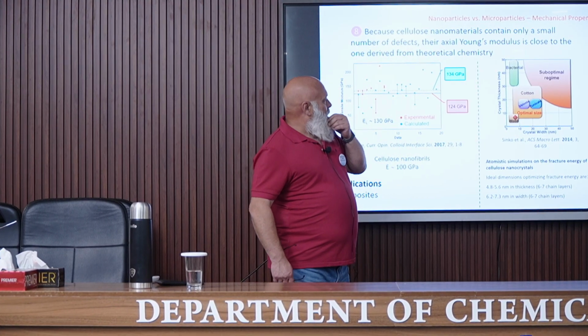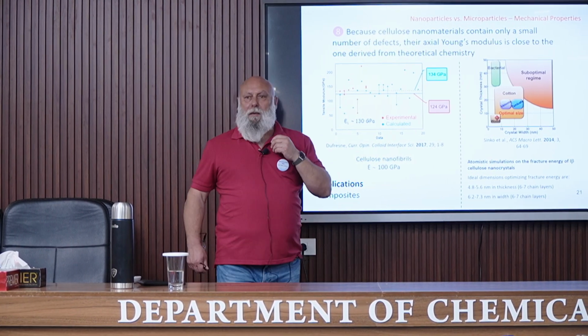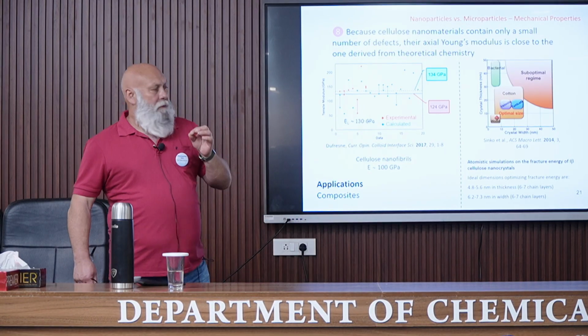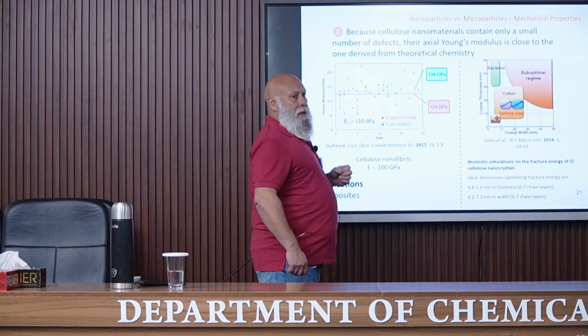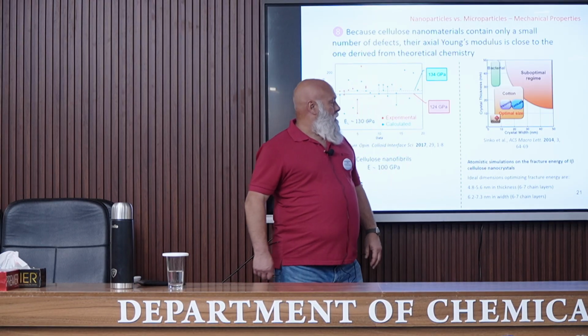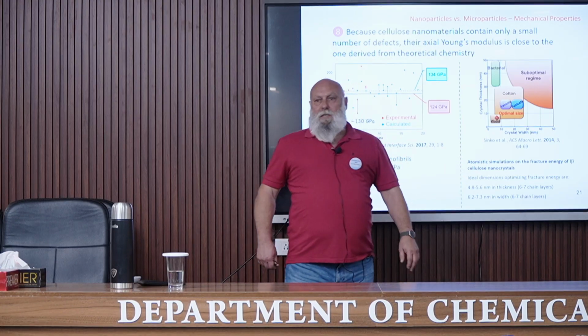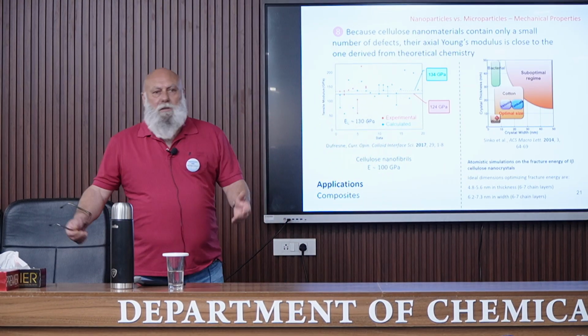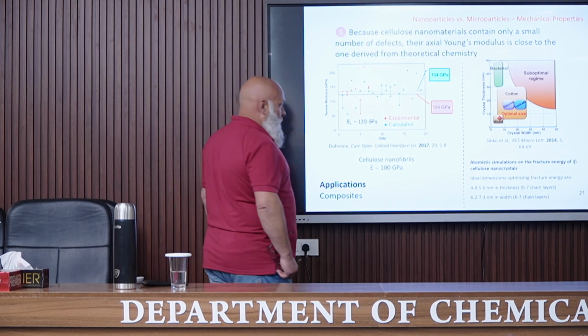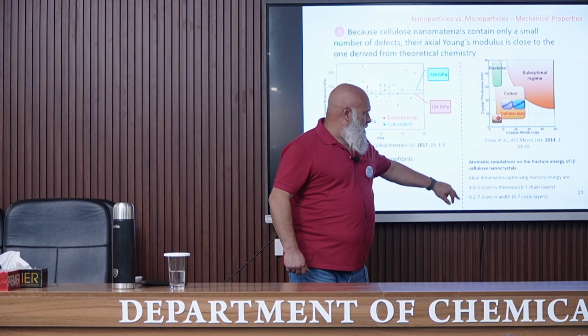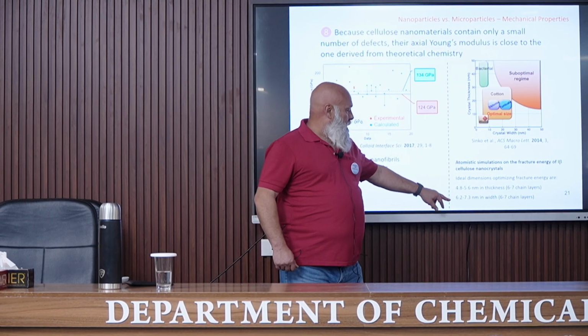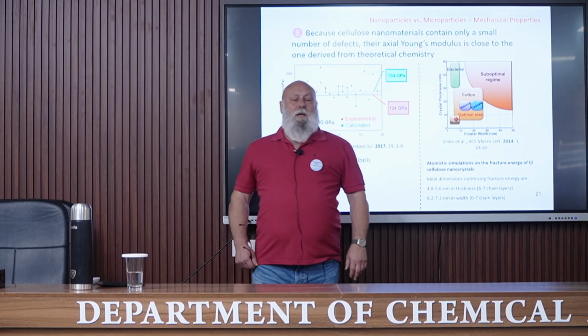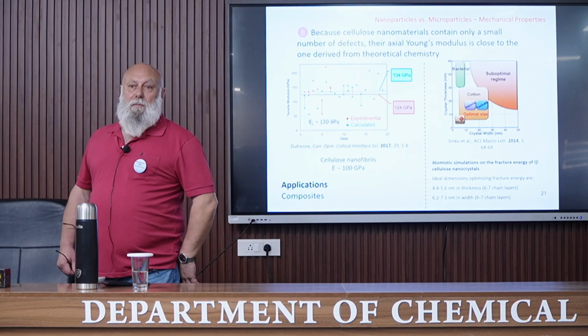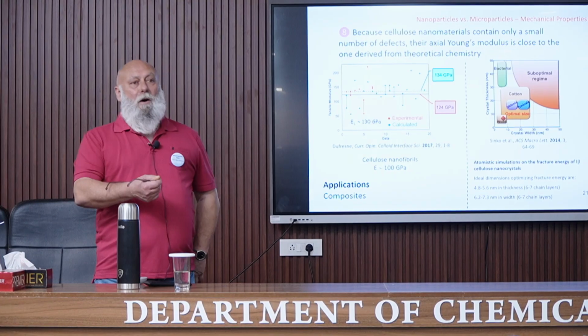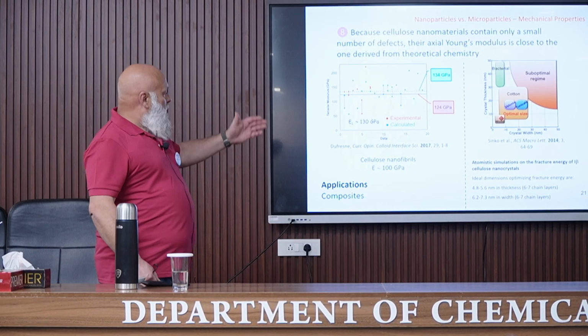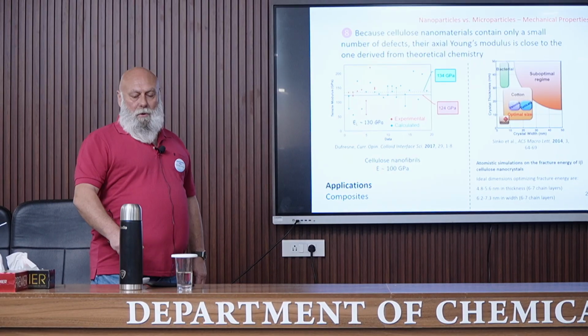This paper is also interesting. In fact, they determined the optimal dimensions of cellulose nanocrystals to obtain the optimal fracture energy of, in this case, Iβ cellulose nanocrystal, so Iβ cellulose nanocrystal extracted from trees. And from the simulation, they found that the optimal dimensions are these ones. And it exactly corresponds to what is found in trees. So it means that nature has already optimized the mechanical properties, in this case the fracture energy, of cellulose.